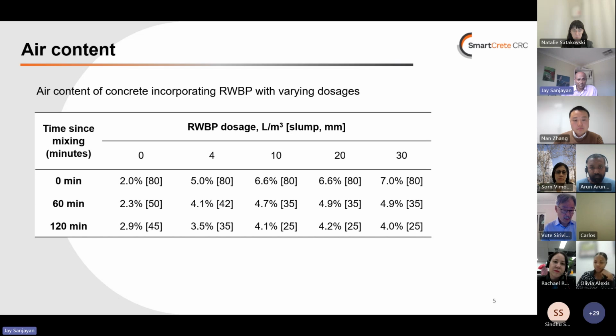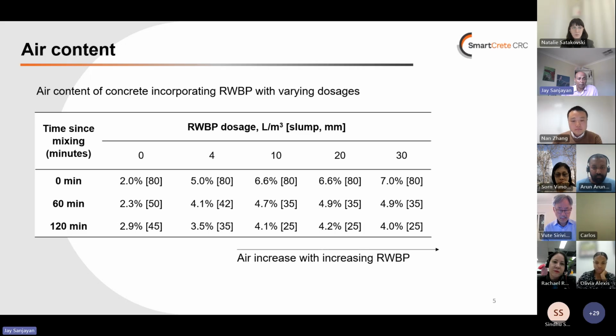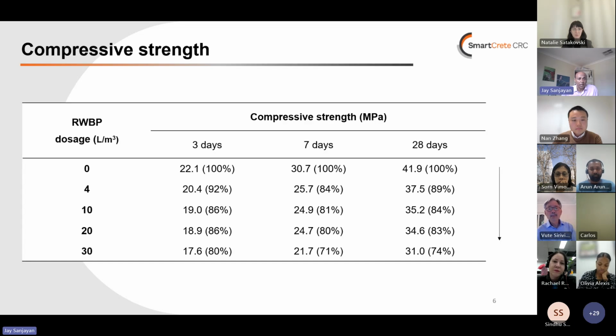But with the waste paint, there's a slight reduction in the air, because the workability is good because we got a lot of air, but the air collapses with time, so we have a slight reduction in the air content with the paint in the concrete. So we are increasing the dosage when we go towards the right, and the air bubbles collapse. So that's why there's some reduction.